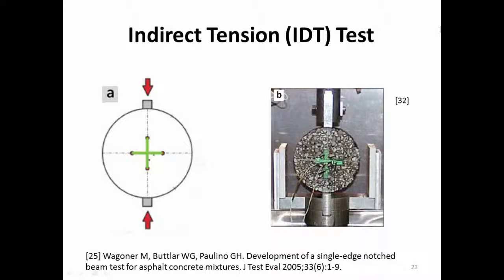Okay. So the first one is called the indirect tension test. You have this cylinder without any notches, you put it into this fixture, and you apply a compression force. The specimen will split to both sides and fail. It's called indirect tension because it's very hard to apply pure, direct tension. So you use compression instead and fail it in tension. It's a complicated idea, but it's the indirect tension test. Because of the convenience of this test, it has been widely used throughout the asphalt industry, not only in the United States, but all over the world.